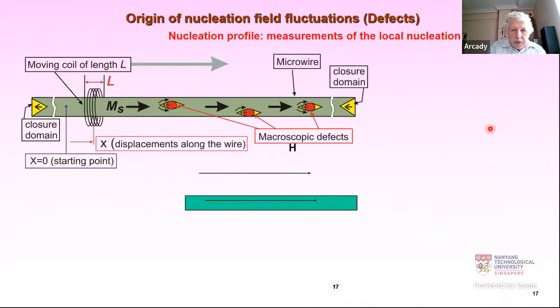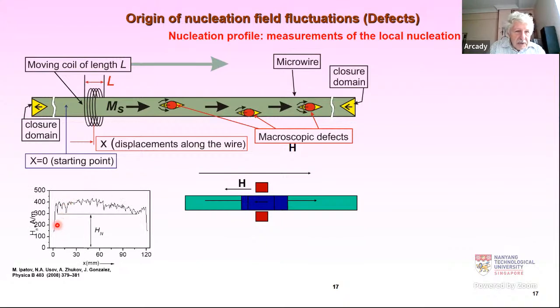The origin of these fluctuations in the nucleation profile, which I showed before, is related to the defects. So now if we move our sample and nucleate a domain wall in different places, by this technique which I showed before, we can get a picture similar to the previous slide.